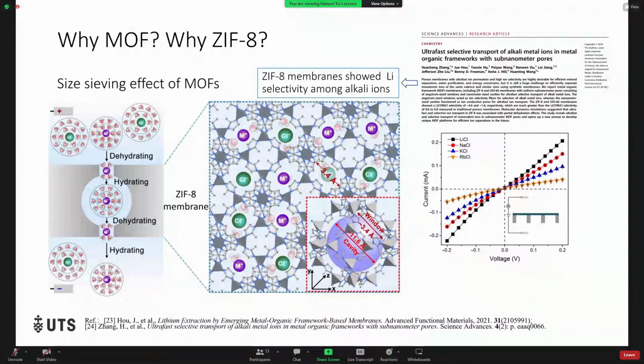However, the ion transport rates of different cations are different. Compared to other cations, the dehydrated lithium ions can pass through ZIF8 first, thus realizing the lithium separation. But ZIF8 has low water stability, so I use dopamine and synthesize the ZIF8 polydopamine mixed matrix membrane to enhance the water stability.